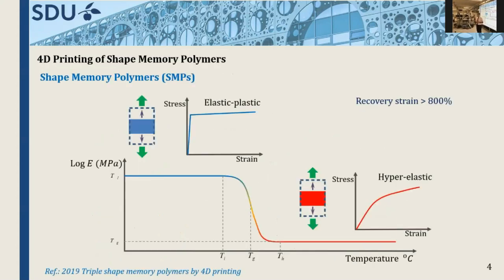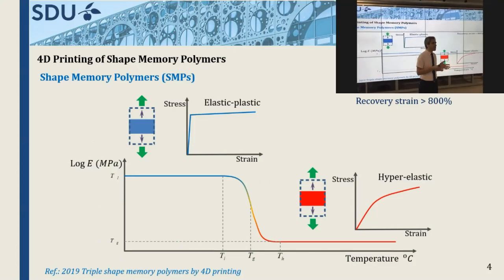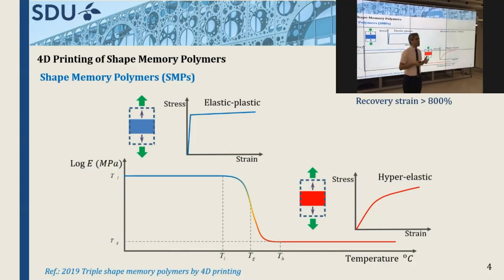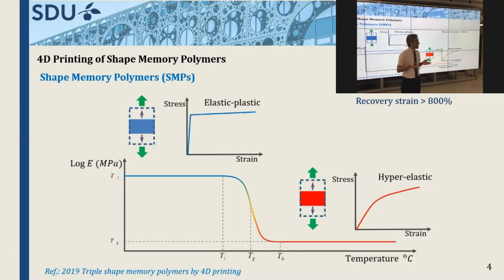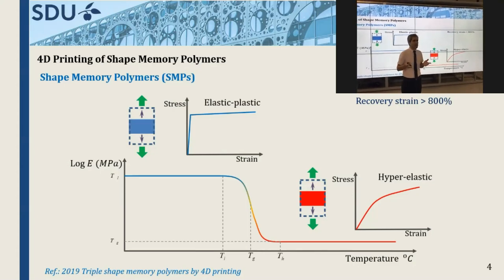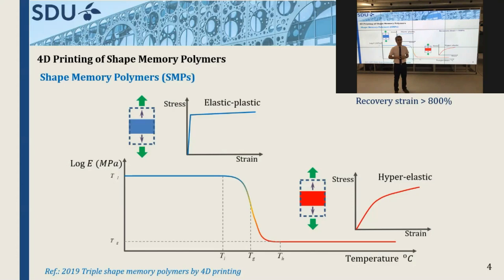Let's focus on the shape memory polymers. As you can see, the key feature of the shape memory effect in shape memory polymers is the transition between the glassy and rubbery phases. Shape memory polymers are stable at low temperature in the glassy phase, while at high temperature they are stable in the rubbery phase. The glassy phase can produce elastic-plastic properties. At the same time, at high temperature, this material has purely hyperelastic properties.